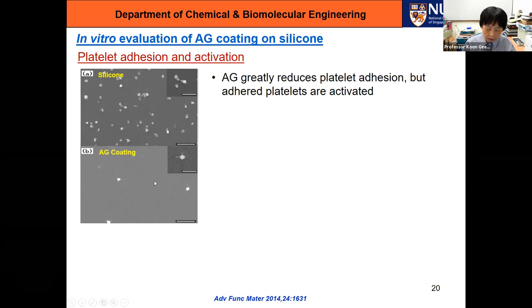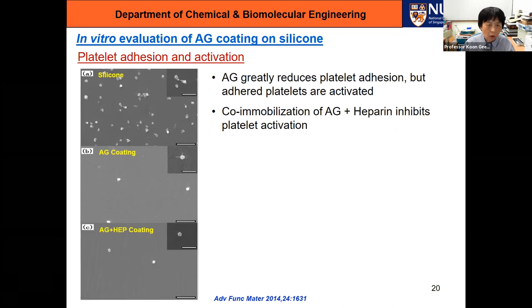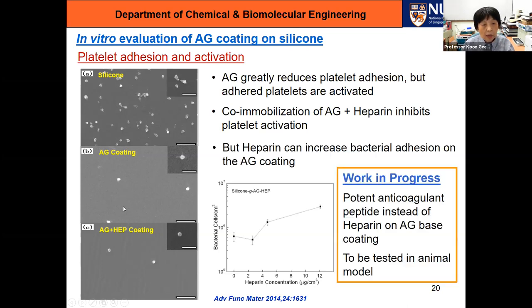So what we did then was to immobilize heparin onto our agarose coating. So when we do the coating, it's a co-immobilization process. And now we look at the platelet, we do not see any activation. So this is good, much better than just the agarose coating. But we have to be careful in how much heparin we use, because if we put too much heparin, then the bacteria adhesion would not be as good as on just the agarose surface, as you can see from this plot here. And we are continuing this work, but we are trying not to use heparin now. We are moving on to an anticoagulant peptide. I don't have all the results yet, so I'm not presenting it now.